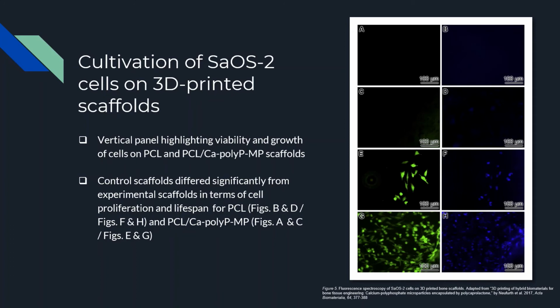For experimental scaffolds, density and cell viability, determined using calcein AM dye, DRAQ5 dye, and fluorescence spectroscopy, was significantly greater for the PCl calcium poly-P scaffold, panels E and G, than for the PCl scaffold, panels F and H.